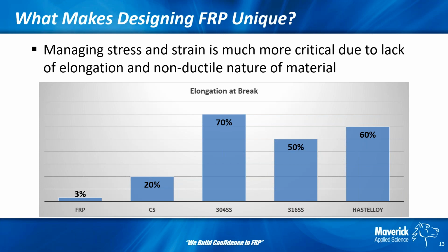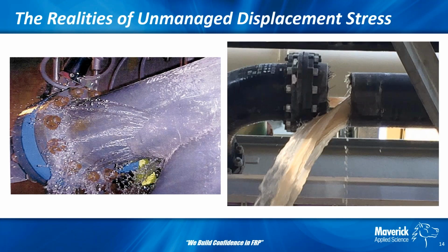And you need to make sure when you're adding temperature to your system that you're not treating that like an expansion case as you would with steel, because steel can locally yield and it relaxes a little bit. FRP, if it gets to that point, now you have failures, which tends to look like this.